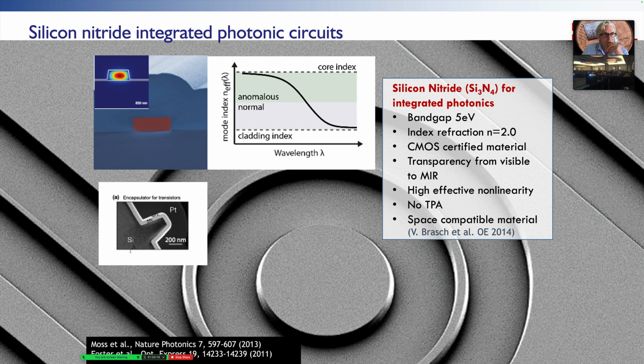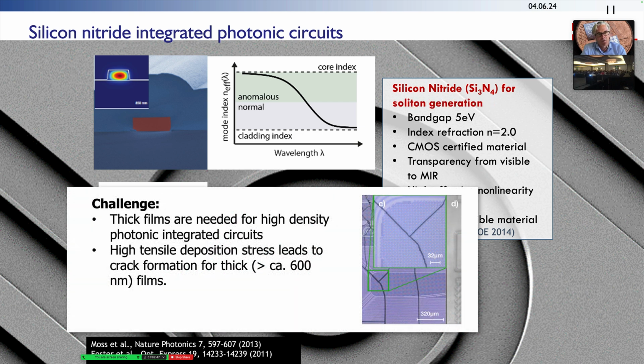Silicon nitride is a material that is well known in the semiconductor industry. It has a band gap of 5 electron volts. It has a moderately high refractive index. It's CMOS certified. Transparency window is from the mid-IR to the visible, and has no two-photon absorption. Plus, it's a space-compatible material. Now, the challenge with silicon nitride, however, has been that this material, when you grow it with LPCVD, so low pressure chemical vapor deposition, which occurs at a high temperature, typically 800 degrees, this material forms cracks. And this crack formation has prevented creating thick layers, thick meaning wavelength scale, to create very tightly confining circuits for many years. And it's over the last decade that these problems have been solved.